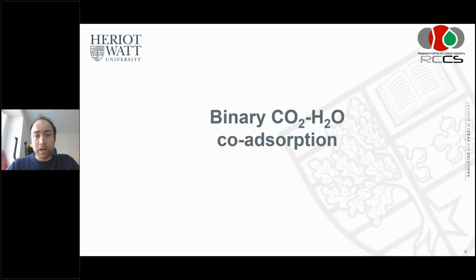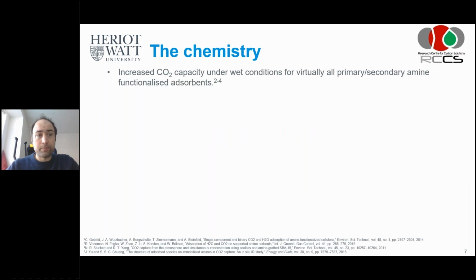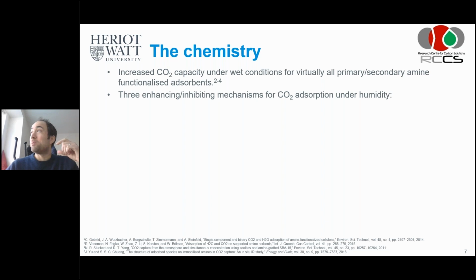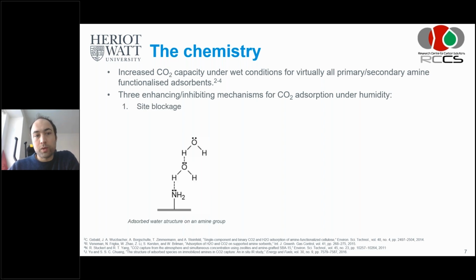So let's look firstly at the binary CO2 water co-adsorption. If we look at the chemistry, what has been observed in numerous studies is that under wet conditions, virtually all primary or secondary amine functionalized sorbents have an increased CO2 capture capacity, especially at 400 ppm, and we will show that later. And we think there are three inhibiting mechanisms for CO2 adsorption under humidity, so in the presence of water. By the way, our thinking has evolved since this presentation. That's based also on work that we're doing now. So there's probably more going on, but this was the original model that we developed.